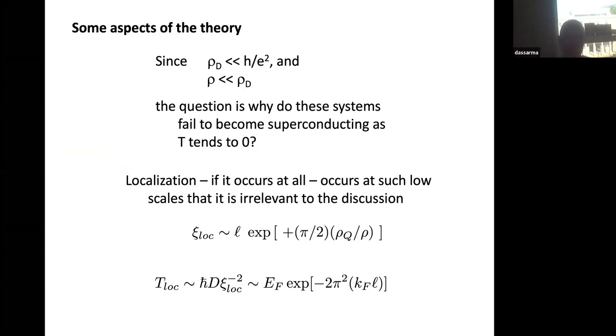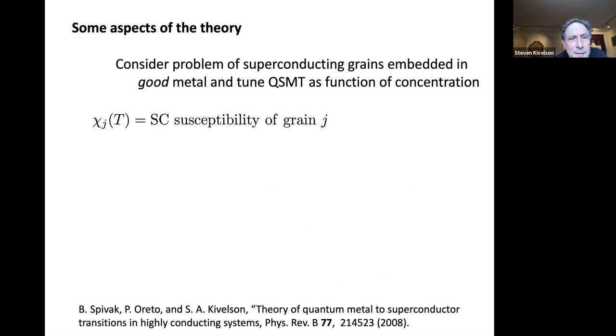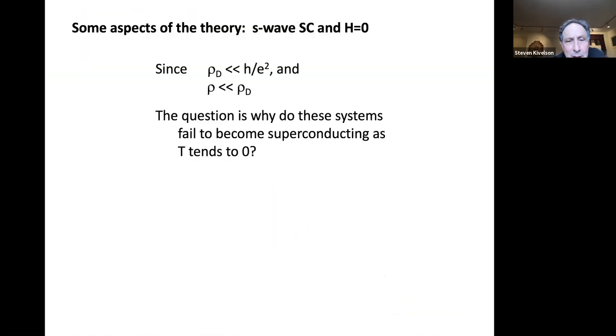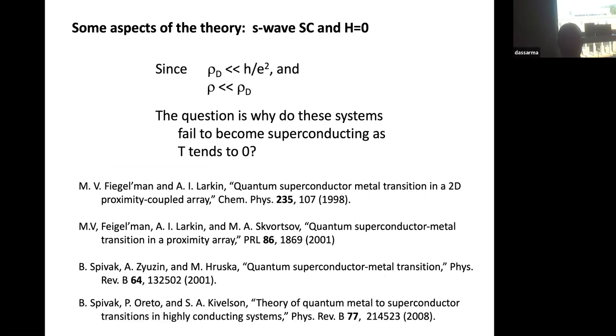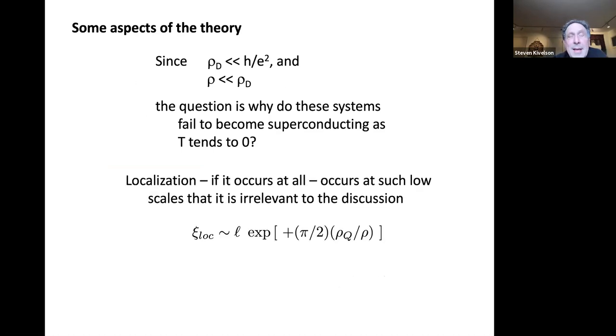So quickly, what is special about 3D? Regular theory allows you to have a metal at T equal to zero. Why is it anomalous? I didn't understand that at all. I didn't get to the theory part, but there's another piece of conventional theory I didn't include, which is the Ginzburg criterion. By the Ginzburg criterion, you would have expected that as Tc goes to zero, the superconducting fluctuation regime asymptotically vanishes. So indeed, a superconductor to metal transition in three dimensions is not surprising. But critical phenomena, that is to say, quantum fluctuations of the superconducting order parameter past the transition, that is anomalous. There is no conventional theory of that. It's more like an anomalous superconductor than an anomalous metal, but I understand the point you're making.